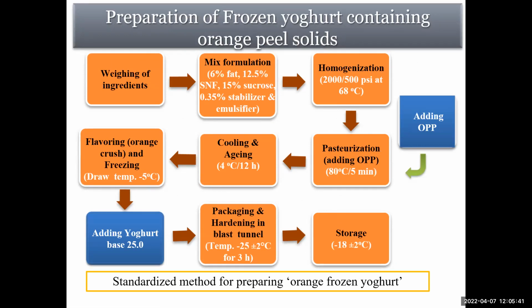The fat and SNF as well as the sucrose content and the stabilizer are the same. Only I am using 1.5% orange peel powder, 2.5% orange peel powder, and 3.5% orange peel powder. After the mixed formulation, homogenization was carried out so that there is no fat layer observed. Then pasteurization at 80 degrees Celsius to kill the pathogenic microorganisms. Then cooling and aging at 4 degrees Celsius.